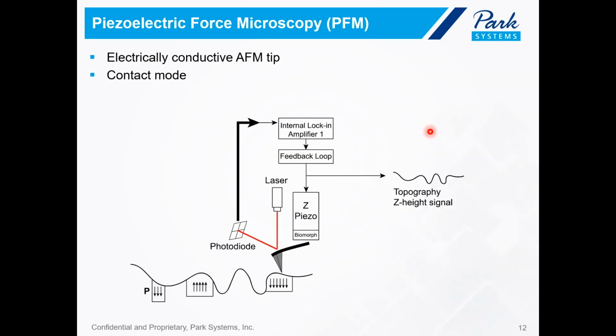Just to give you an idea of how PFM works inside a Park AFM, I have this slide here showing some of the key components of our machine, so we can see how our instrument is able to give us these signals. I want to point out that this schematic is showing imaging in contact mode. Conventional PFM is typically performed in contact mode. So keep this in mind, because when we talk about pinpoint mode, you will find the difference between the conventional PFM and the pinpoint PFM. And the imaging is performed with an electrically conductive tip right here.